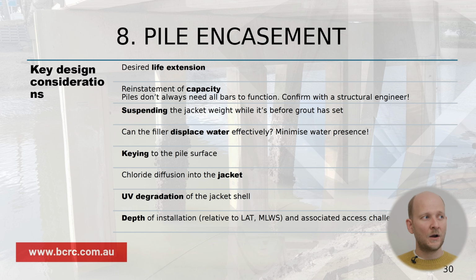And also, once you are pouring in that filler, would it displace water effectively? Remember, we are in a tidal zone, so the water will be there, and we need to think how to minimize water presence. Then this grout, in some cases, could be epoxy, but most of the time we're talking about cementitious material. How could it key to the pile surface? I wouldn't recommend relying simply on the roughness of the concrete to provide sufficient keying to grip to the pile.